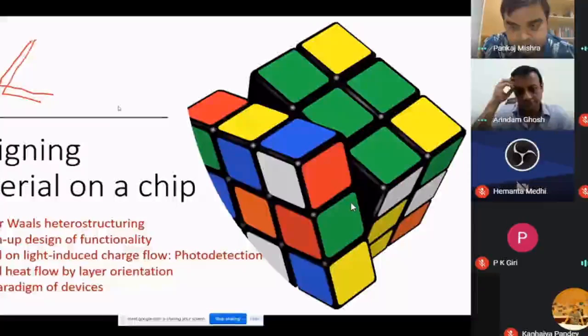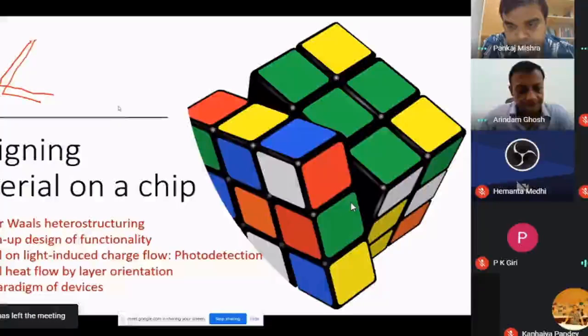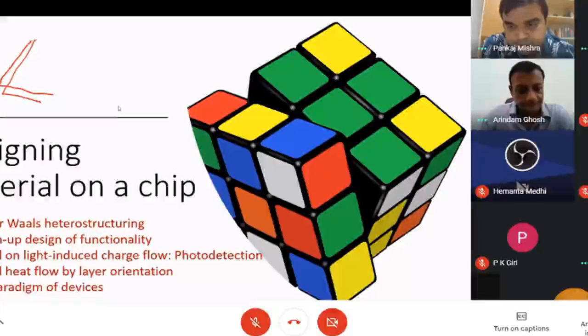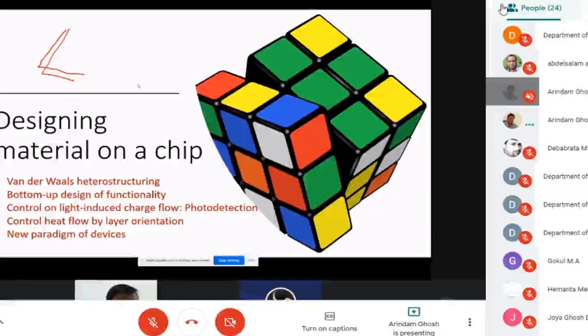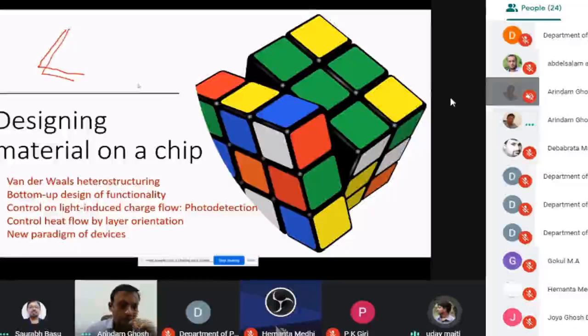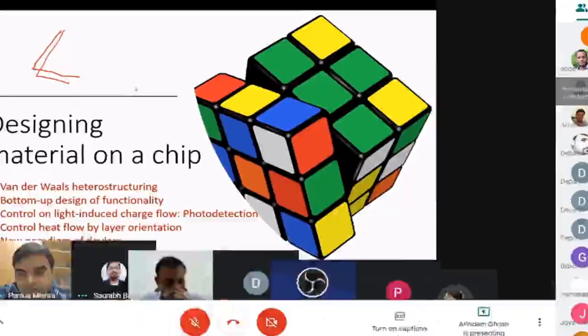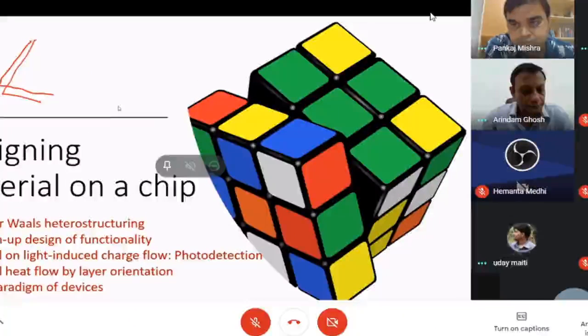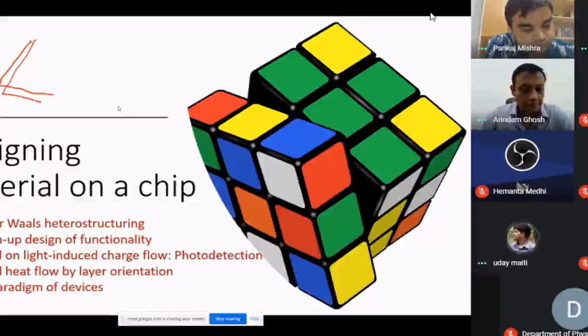Uday? May I have a question? So, this is Uday from Department of Physics. I have some question regarding whenever you are transferring any of your 2D materials like graphene on the SiO2 substrate for device fabrication. There is always chance of trap charges in between this graphene and the surface charges, and it leads to some charge puddle. So my question is whether this formation of heterostructure can actually minimize the effect of these trap charges, I mean, due to the screening effect.